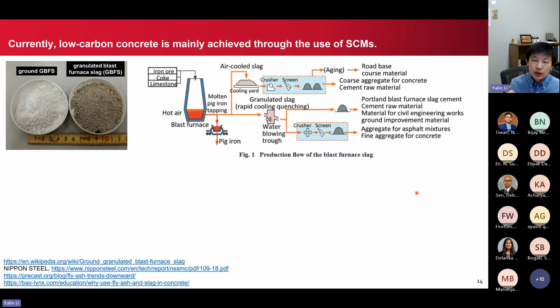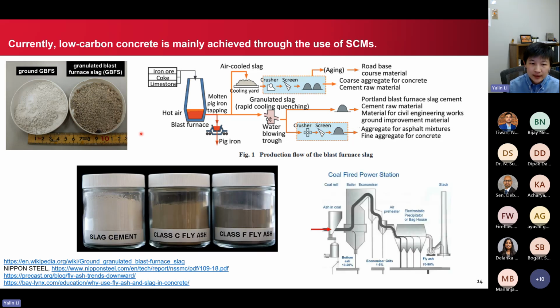The two most widely used SCMs at this stage: the first one is the granulated blast furnace slag, or GBFS, and people usually just call it slag. This is a waste product or byproduct produced from the steel industry. It's usually a waste, and there's not too much use of it, so using slag in concrete production is actually very beneficial. The second is fly ash, which is the ash product from your coal power plant. When you burn coal to generate electricity, the ash can be used as an SCM in your concrete mix.